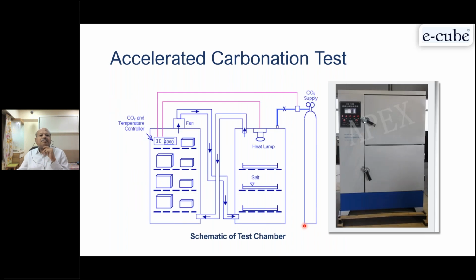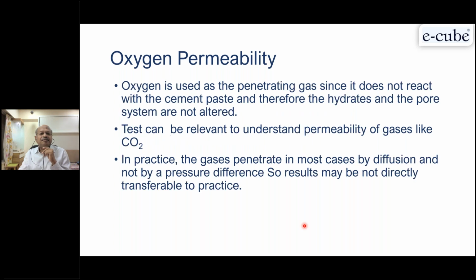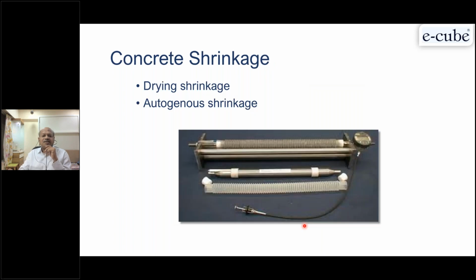This is the arrangement for an accelerated carbonation test, because we have a lot of industrial pollution, and even on the road a lot of CO2 is coming up, which also affects your infrastructure. So that needs to be checked. Earlier we were saying hardly 0.5 to 1 mm per year, but now within say 5-6 years we see 10-20 mm carbonation has taken place. So that also needs to be considered for proper selection of materials on this carbonation test. Oxygen permeability is similar to this. Then autogenous shrinkage: since we are working with very high binder content, there is a possibility of autogenous shrinkage. There is a test given in ASTM to test the paste, whatever paste we are using, to find out the autogenous shrinkage.